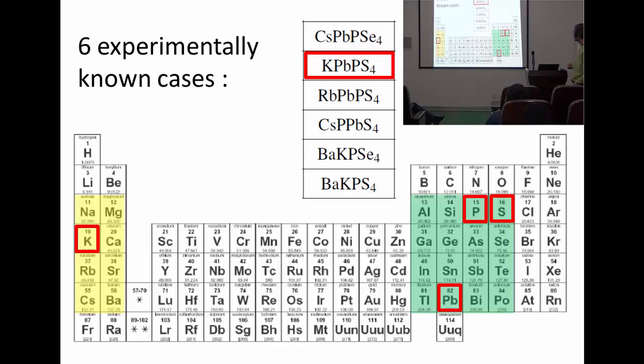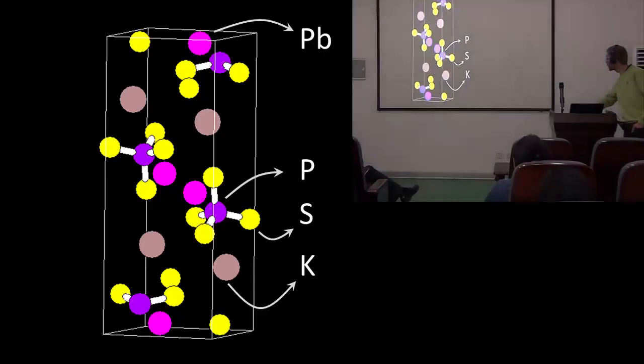And the example I take is potassium, lead, phosphorus, sulfur. That is an experimentally known quaternary Zintl phase. That's the crystal structure of it. So it's an orthorhombic crystal. You have these tetrahedra of phosphorus surrounded by sulfur. There are potassium atoms dispersed into that structure and lead atoms dispersed into that structure.